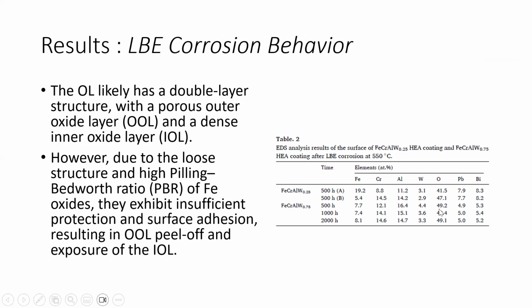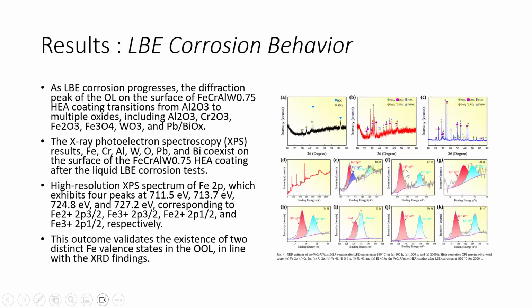So this table shows the XRD analysis result. So we can see the different elements at different times. And as LBE corrosion progresses, the diffraction peaks of the oxide layer surface of the sample coating transition from aluminum oxide to multiple oxides, including aluminum oxide, chromium oxide, iron oxide, and others.